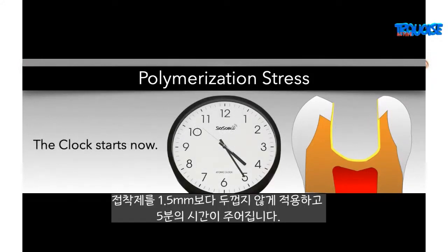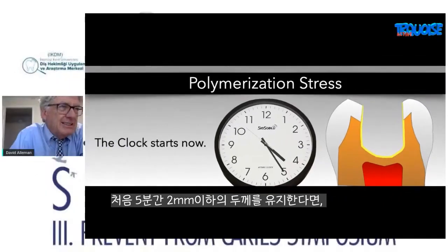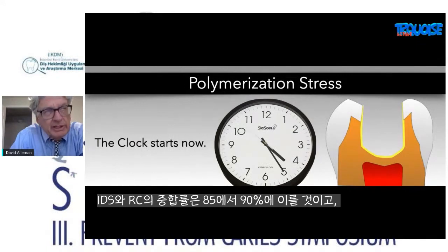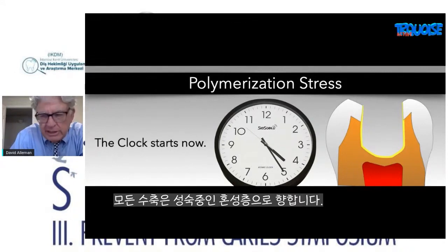When you put your adhesive, you've got 5 minutes that you don't want to get thicker than 1.5 millimeters. If you stay less than 2 millimeters in that first 5 minutes, then the polymerization of the IDS and the resin composite is to the 85–90% polymerization, and all of that shrinkage has gone towards the developing hybrid layer.